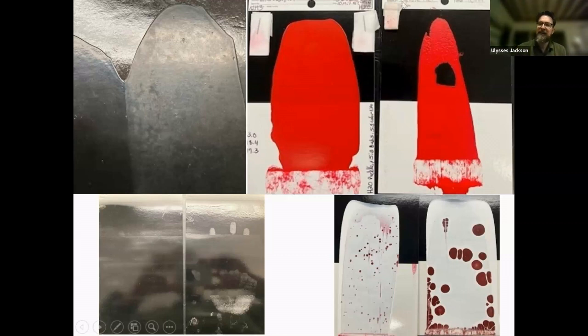Here, you're testing chemical sensitivities. So this test here, there's a water drop left on the surface, and you can see this coating on the right blistered off. This coating on the left had no damage and very little sensitivity here with the chemical sensitivity, ammonium water. This one has a little more. Happy to say this is our paint and this is someone else's.